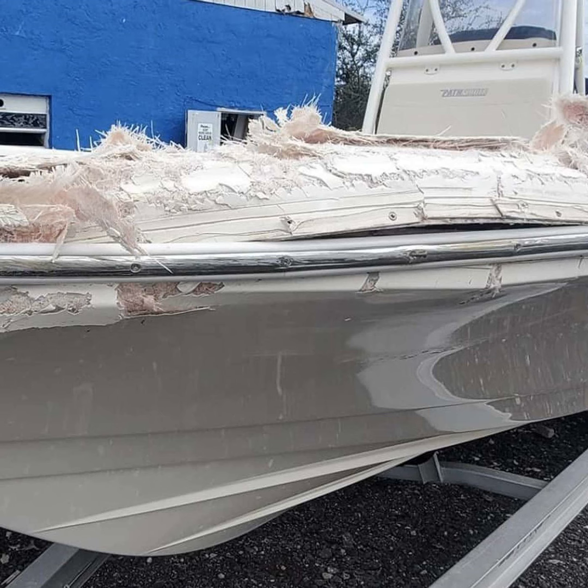And so you have to keep in mind when you do that, you have to remove enough glass initially to let you put enough new glass to have the strength that you need. So don't be shy when you're grinding. Depending on where it is, if you're just tabbing, then you can grind for adhesion. That's fine. If you're tabbing stringers to a hull or something like that. But if you're doing a repair where you're going to follow it up with a cosmetic repair and you're looking for the best results that you can get, then you need to keep in mind that if you don't grind